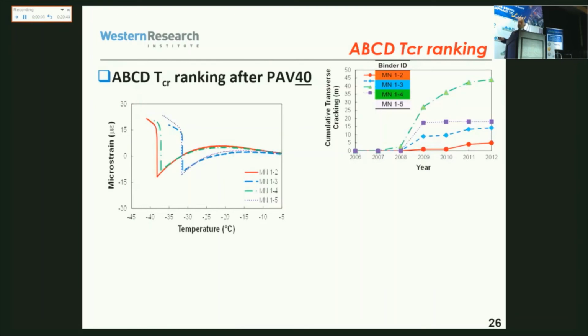So we did some ranking using the critical temperature, the temperature at which the binder will fail. We took some data from Minnesota, and you have seen this before, with the MN1-4, which was re-refined engine oil bottoms, REOB, modified, and cracked very badly in the field. Then there are other binders, and that one, for example, is polymer modified and performed very well. We did the ranking and found that it ranks pretty well, except for REOB. So there is something else here that we need to understand.